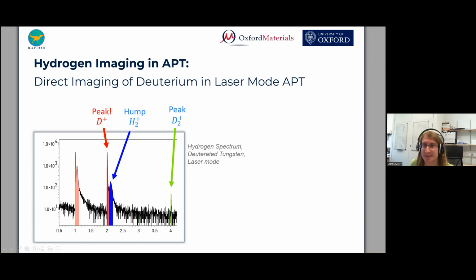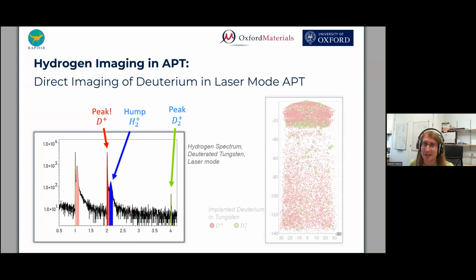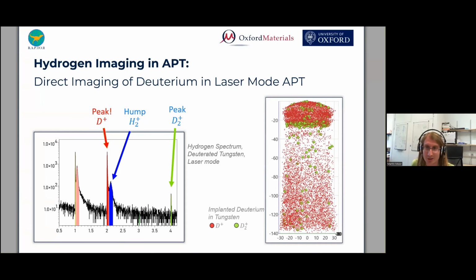And what this does is it's enabling hydrogen imaging in laser mode. So what you see here is what I claim to be the first successful direct imaging of deuterium in laser mode APT, with the full resolution, with the full sensitivity, without the need for any further tricks like peak decomposition. What you see, by the way, is an implanted deuterium sample. So the deuterium is following a depth profile. There's an implantation front. Not a lot of deuterium here, but then it's a radiation damaged sample, so there are trapping sites where it's staying here.